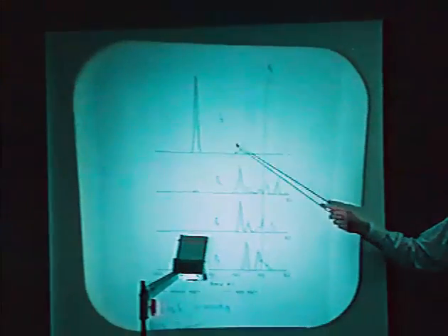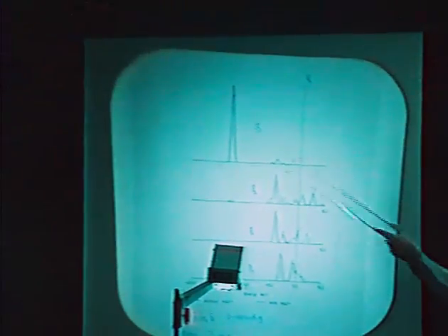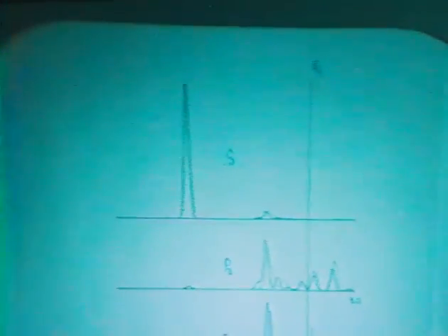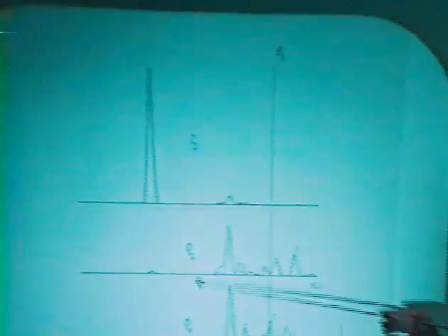Because this is the isolated sulfur, and all that differs from the isolated sulfur plot is the contribution to the molecular orbital. And you see, well, that's only a very small peak. So literally it hardly contributes to the bonding. So the conclusion is that the S orbital is not important in the bonding to an iridium cluster. Well, let's look at PZ.